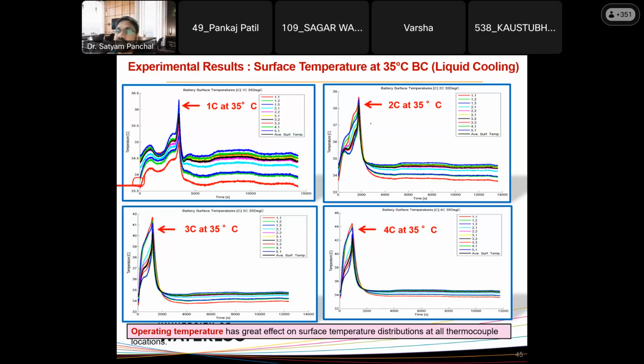Thank you. So for 2C, again the starting temperature is 35 and the ending temperature you can see is around 38 degree. For 4C, the temperature increases from 35 all the way to 44. Instead of 4C with air cooling, where the temperature went all the way to 60 degree, now it is around 44. So we got around 15 degree C difference with the water cooling method.